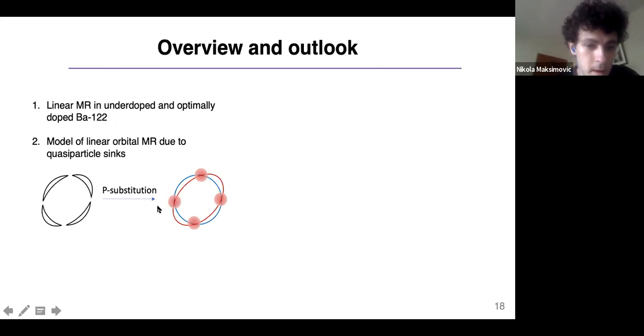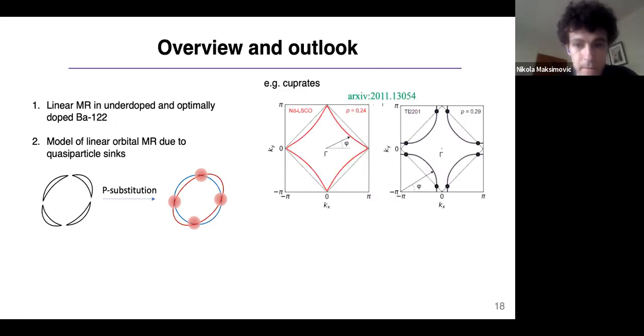I will just mention that, while these calculations have been done for barium-122, we might expect this mechanism to generalize to other materials. So for example, let's say the cuprates, you may have regions of the Fermi surface that have large curvature. This is a tight binding calculation for neodymium-doped LSCO. Or you may have regions of the Fermi surface that have a very high scattering rate. And these can both act as quasi-particle sinks and in fact give rise to linear magnetoresistance.